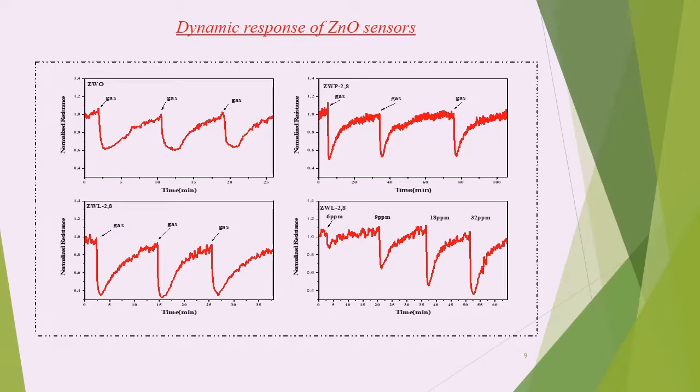Here we present the electrical measurements made on the zinc oxide samples for different gases. The dynamic response characterization of zinc oxide without oil and with paraffin oil and lavender oil at concentration 2.8 showed that the prepared sensors exhibit continuous and intact response recovery curves. The three reversible cycles of the normalized resistance illustrate that the prepared sensors exhibit good stability and repeatability. For zinc oxide with lavender at concentration 2.8, the normalized resistance curve toward various concentrations of ethanol at 180 degrees Celsius shows that the response increased with increasing ethanol concentration.